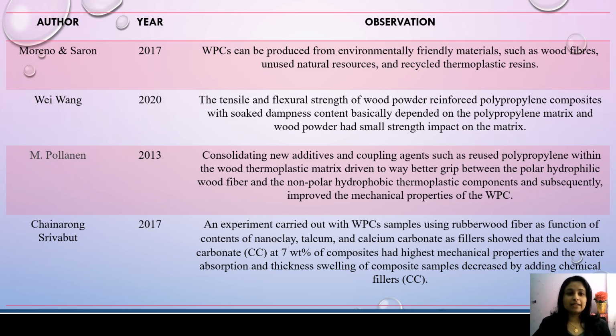Besides that, an experiment conducted by Chainarong Srivabut in 2017 with WPC samples using rubber wood fiber as a function of contents of nanoclay, talcum and calcium carbonate as fillers showed that calcium carbonate at 7 weight percentage of composite had the highest mechanical properties, and the water absorption and thickness swelling of composite samples decreased by adding chemical fillers, which is calcium carbonate.